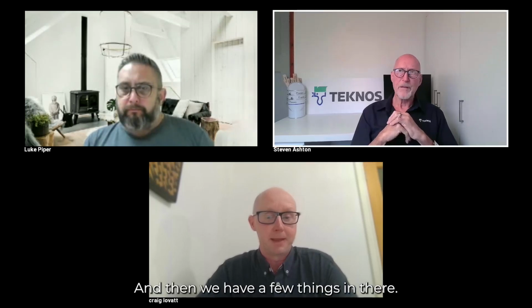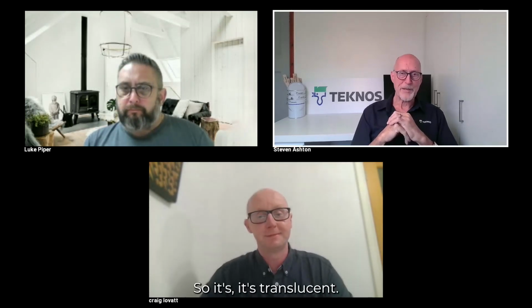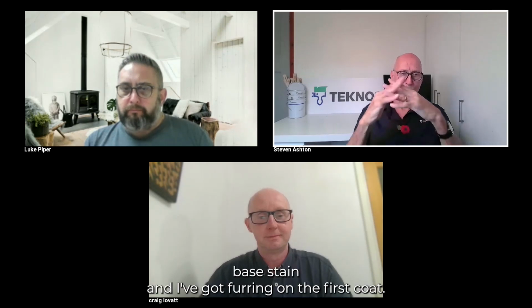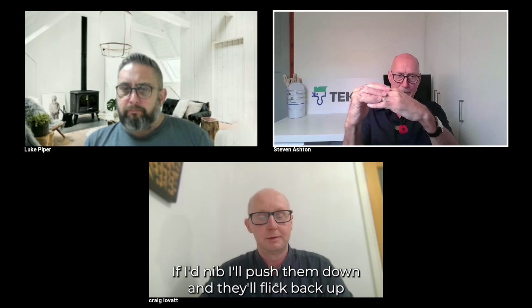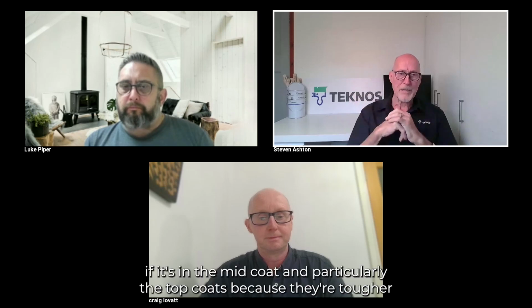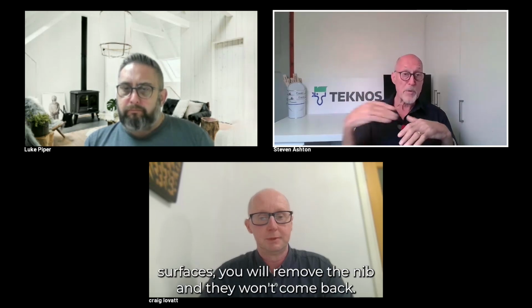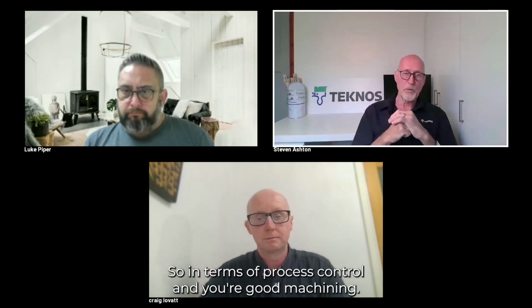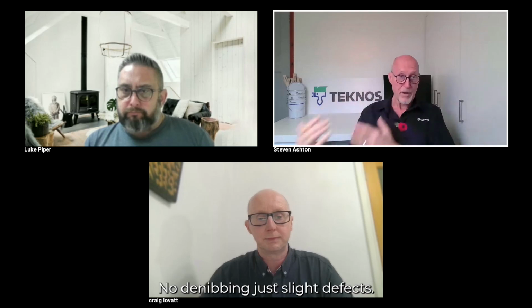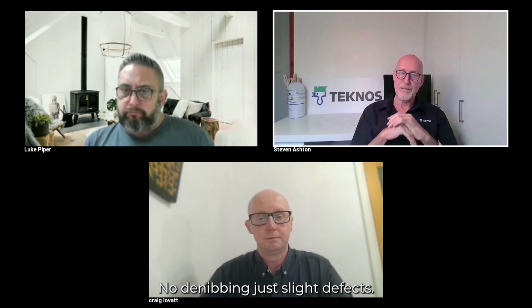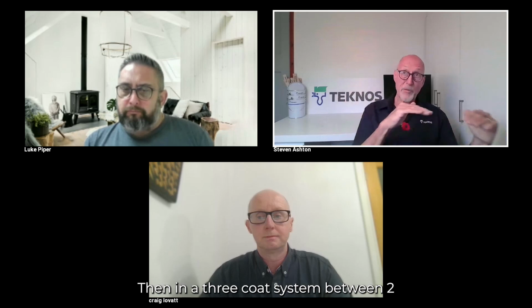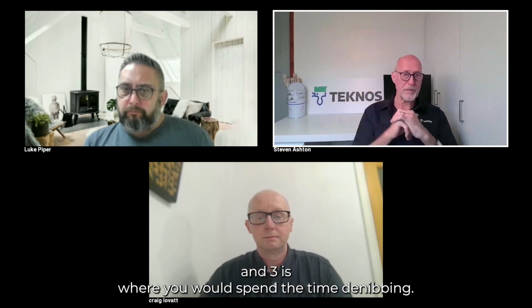Yeah. And then we have a few things in there. So if it's a translucent base stain and I've got furring on the first coat, if I denib, I'll push them down and they'll flick back up. If it's the mid coat, and particularly the top coats, because they're tougher surfaces, you will remove the nib and they won't come back. So in terms of process control and your good machining, no denibbing, just slight defects, then in a 3-coat system, between 2 and 3 is where you would spend the time denibbing.